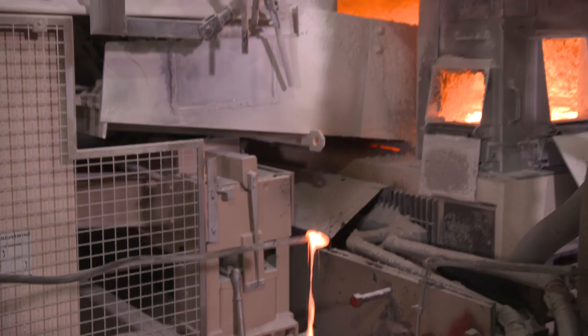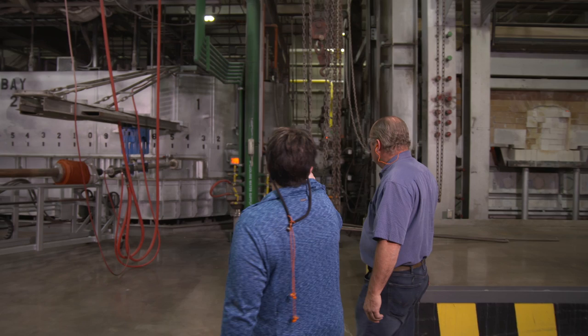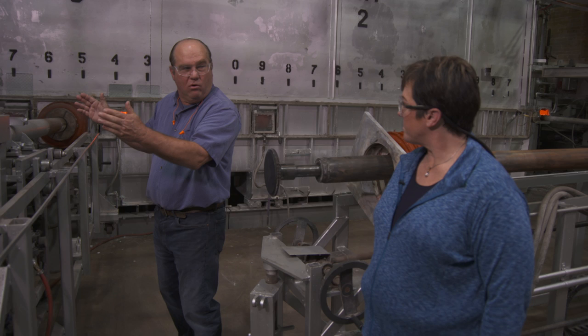Looking into the furnace, the material has already turned molten. All of it is filled with molten glass. When the glass comes to the canal, it flows into the tin bath, where tin is melted to a depth of two to four inches. As the glass pours in about a quarter inch thick, it spreads out over the molten tin, and top roll machines on the very edges stretch it to the width and thickness needed — like taffy being pulled into a sheet.